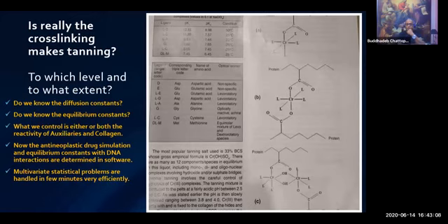And C represents the dinuclear chrome complex, which forms a bridge connected with the carboxylate side chains of aspartic acid and glutamic acid. It is type C that is usually believed to be responsible for the increase in hydrothermal stability after chrome tanning. That means the boil test, as a function of how efficiently we can make these binuclear, trinuclear complexes and cross-link them in the different areas.